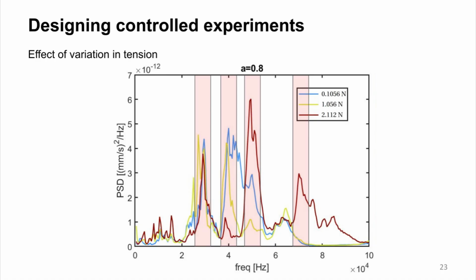For the first of the peaks, around 30 kilohertz, for 3 of the tensions I tried for this metamaterial, the peaks mostly agree. Whereas for the second peak around 40 kilohertz, the peaks don't agree under different tensions that I've tried. At the 50 kilohertz mark, again the peaks don't agree, and there is a peak which isn't present at all in 2 of the tensions, but is only present in the 2 Newton tension that I've tried this metamaterial under.